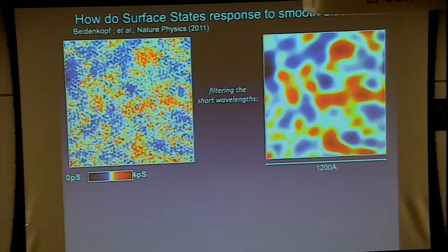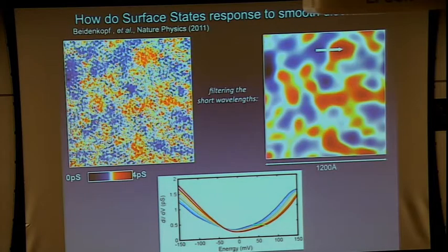which is varying the electronic properties of your sample. Now, what's kind of fun is that we can actually see the effect of this not just looking at the conductance map, but actually looking at the wavelengths. Okay, what do I mean by that? So remember, this is the variation of the spectra. This is showing you the density of states as a function of energy. This would be a gapped spectrum. This was a simple semiconductor. It has states inside the gap. This is coming from the surface state. And you can see the band structure is varying, roughly speaking, on the atomic scale.